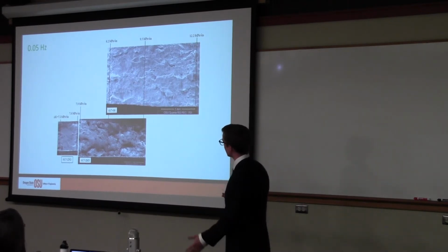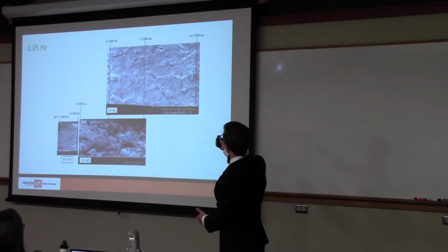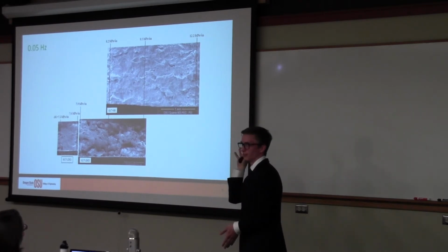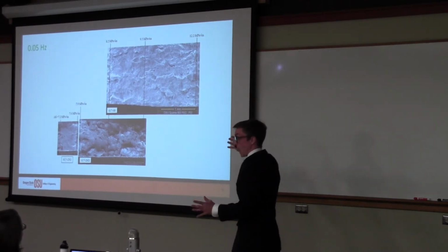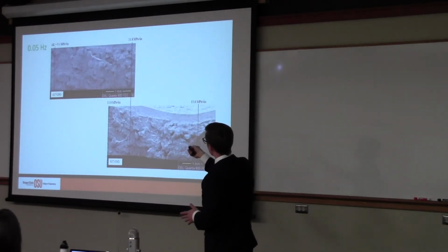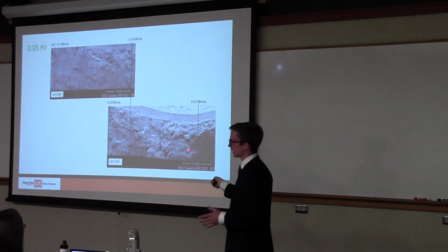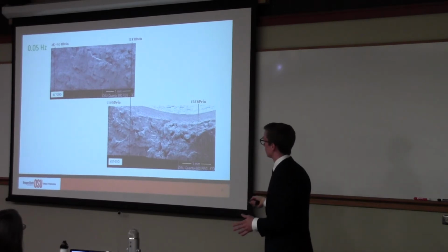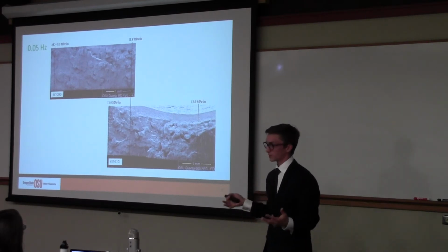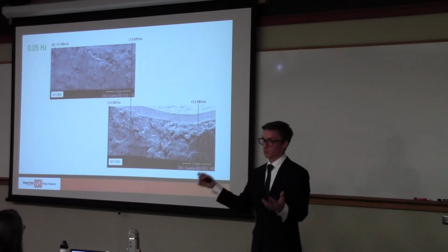Then if we go a little bit higher, see, right now we're a little bit below where the low frequencies start to break away on the first plot that I showed you. You guys remember that? Where it starts to break away, it gets really fast, it's really bad. We're below it. And so if we go a little bit above it, it's 11.8 and then 15, with totally different character. That's what happens when you break away. When we look at it in a different way from the profile side, what looks like a void coalescence mechanism that is time dependent.